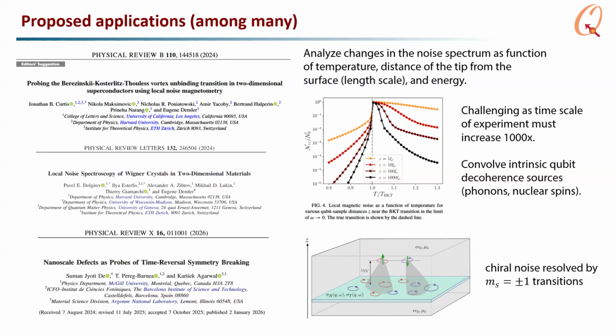Depending on whether you use amplitude feedback or frequency feedback to stabilize your AFM set point, you can get closer to certain samples. Yes, the ultimate technique may become better someday. I think people at room temperature have shown less than 25 nanometers, from Christian Degen's group, but I think it's going to be hard.